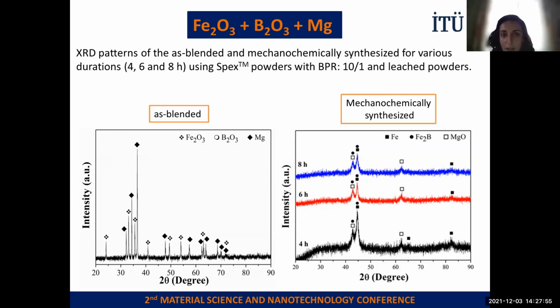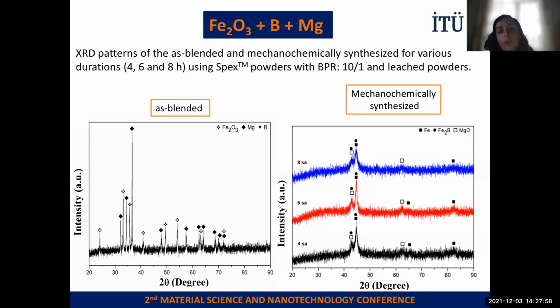And also the second batch consisted of the iron oxide, boron, and magnesium. Similar XRD patterns are seen here. The as blended powders consist of just our initial raw materials. After the milling with various durations, iron boride and magnesium oxide peaks were clearly seen, and it shows us that the iron boride synthesis was successfully conducted after the mechanochemical synthesis. But we still have magnesium oxide peaks. Also we will leach it to remove the magnesium oxide phase from our nanoparticles.